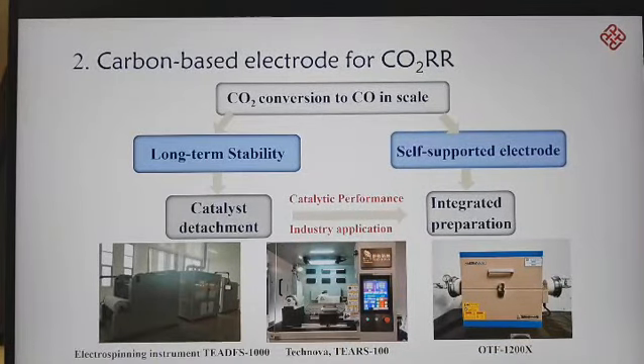As we mentioned before, from the perspective of product selectivity, CO2 conversion to CO at scale is feasible. However, it also faces a significant challenge. The preparation of large-scale electrodes for industry is difficult, and the stability of scale-up experiments is poor. Currently, electrocatalysts are mainly in powder form, prepared into electrodes through the traditional coating process, which can lead to catalyst detachment during long-term operation.